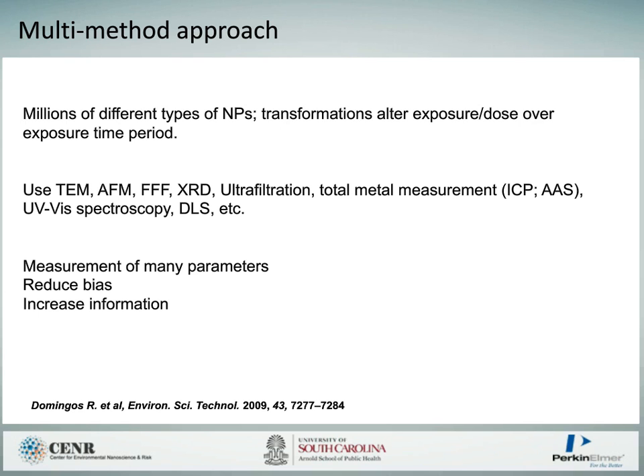If you look at a familiar technique like dynamic light scattering, that is often biased to large aggregates. What you'll see by that method is large aggregates, while ignoring the fact that there may be dispersed particles or dissolved iron or other shapes or precipitates of the original material. So by using a whole range of different techniques, we can measure a number of parameters, because we're interested in composition, size, shape, and so on. We also reduce the bias so we can understand whether particles have aggregated, dispersed, or dissolved, and increase the information content of our samples before, during, and after exposure to organisms and to cells.